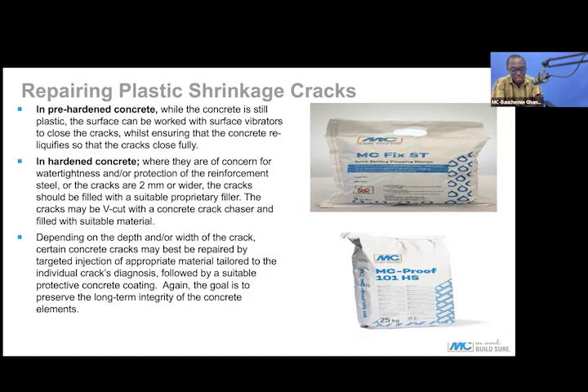And sometimes, when you have a lot of cracks on the surface, like the picture I showed, you may have to remove the cover on the surface and probably recast it. You have to remove the cover and recast the surface to restore it, because when you have reinforcement closer to the surface and you have such cracks on the surfaces, exposure conditions like carbonation or chloride attacks are very, very common. So water and dissolved salt will enter these cracks, then they have access to the reinforcement and they begin to react. Then corrosion sets in, and the reinforcement begins to lose its potency. So once you notice that these cracks are a lot on the surface, you can just remove the surface concrete, take off all the cracks, and replace it with concrete or a structural repair mortar to restore the integrity of the structure.